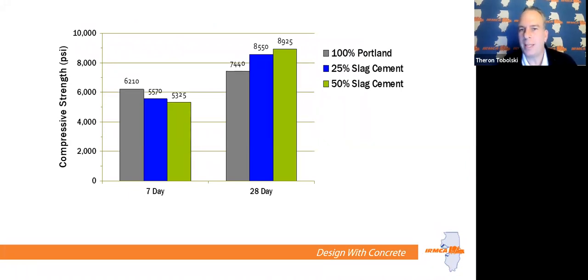Slag or fly ash used in the mix also is going to change how the concrete acts. And I feel like this is a good chart to show you. So we see here under 7 days, the gray is a straight cement mix, and the blue is a 25% replacement with slag mix, and the greenish color is a 50% replacement of slag. So you can kind of see in the 7-day range, the straight cement mix outperforms from a strength standpoint compared to the slag replacement. But when you get out to the 28 days and even longer, the slag 25% and 50% replacement actually outperforms the straight cement mixes.